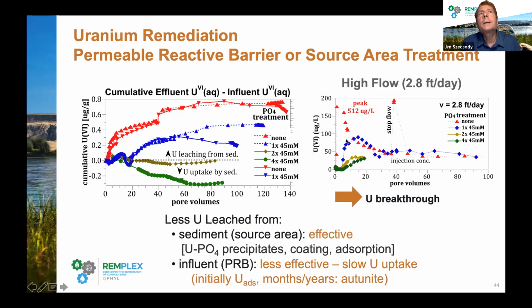Then if we go over to the right diagram, where I'm plotting just uranium concentration in a column experiment with untreated, low, medium, and high treatment, to see if this is actually how a permeable reactive barrier would work. These experiments were at a high flow rate. With more phosphate treatment you do get some effect as a permeable reactive barrier, but it doesn't work terribly well. So the phosphate treatment is not very effective as a permeable reactive barrier.